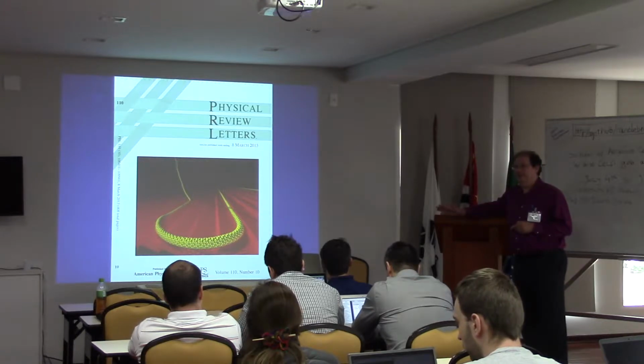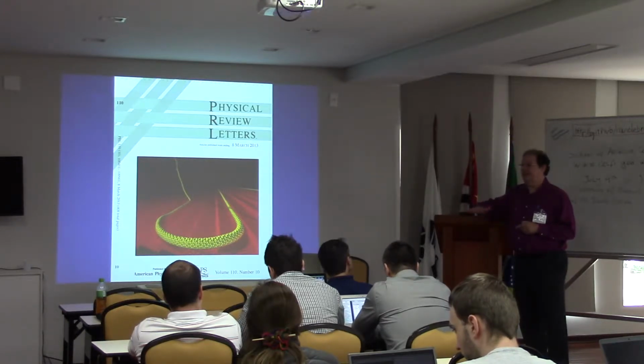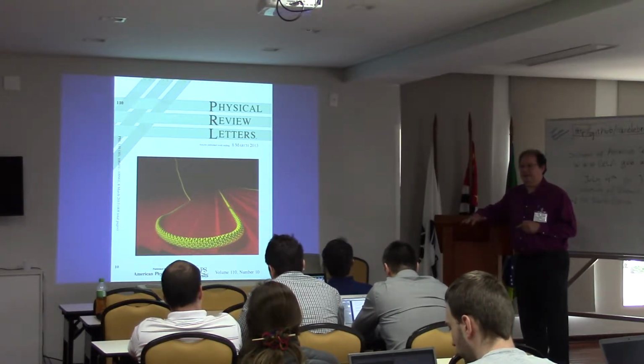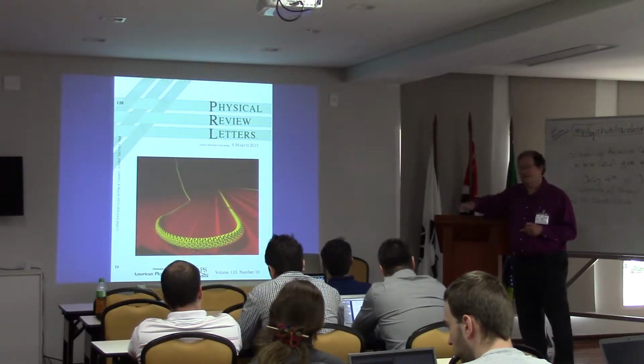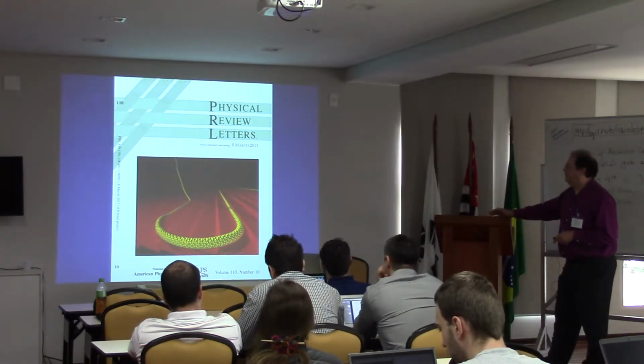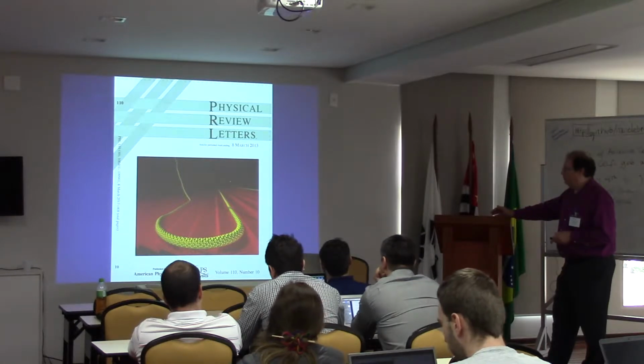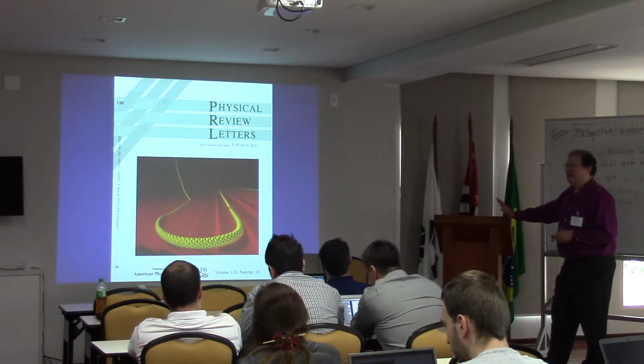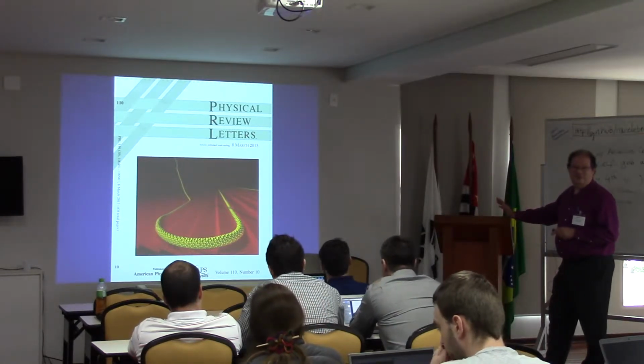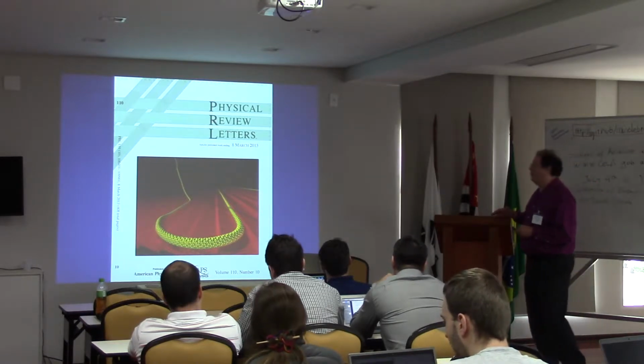It's almost the same dynamic, but graphite is not as sticky as the silicon oxide. It slides more, but the dynamic is almost the same. We got, again, the cover of the PRL. See, you need to make nice figures so you can compete for the cover.